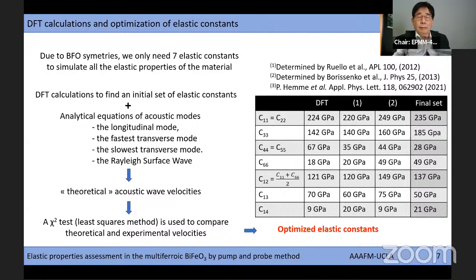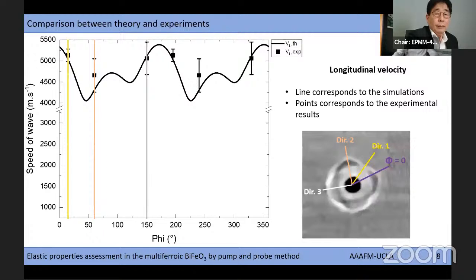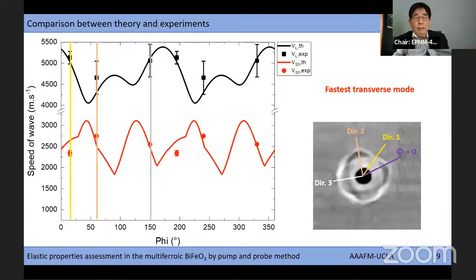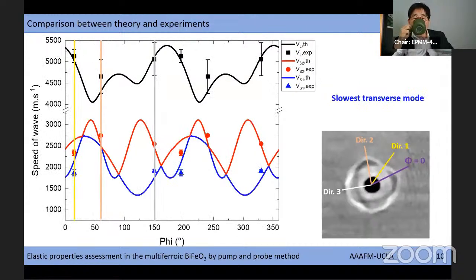Here you can see the final set of the obtained values. Now I present the calculated and experimental velocities associated with the three bulk waves and the surface wave as a function of the phi angle. This black line corresponds to the calculated longitudinal velocity, and the squares represent the experimental points. The vertical lines are associated with the three directions of measurement. Here is the comparison for the fastest transverse mode. Now the experimental and calculated velocity for the slowest transverse mode.